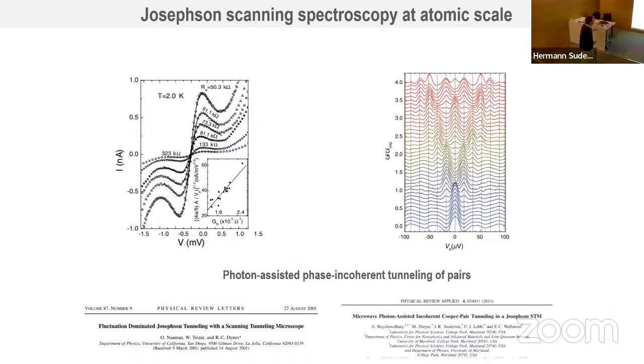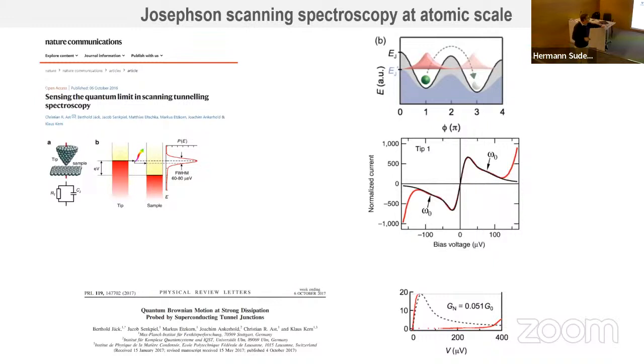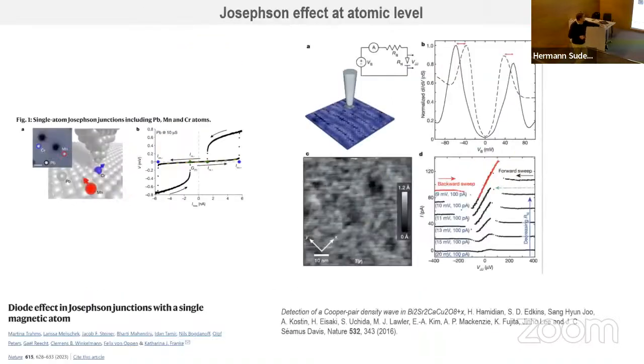Now, people have been doing these kinds of experiments for a long time, but essentially, you always get these curves here. And there is a very strong interaction with the photon field, as usual, when you have a superconductor. And there are some features which are explained by this interaction with the photon field. And essentially, you get a conductance which is pretty small and which is within a gap which is open. So within a region of current where there is nothing, just at zero bias, you get a finite conductance. And there are people who have been, for example, very recently, Katarina showed that you may make a sort of a diode using this kind of effects by using Shiba impurities.